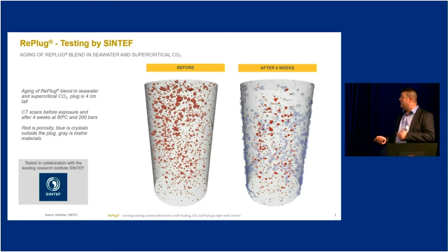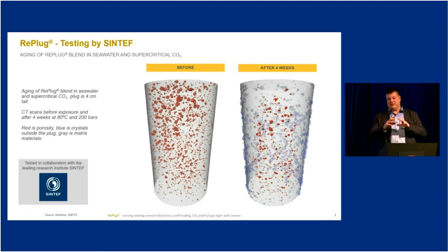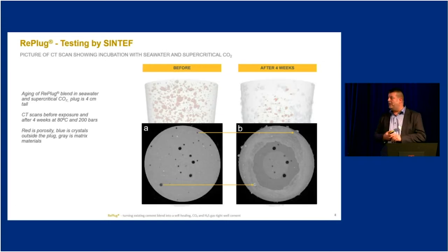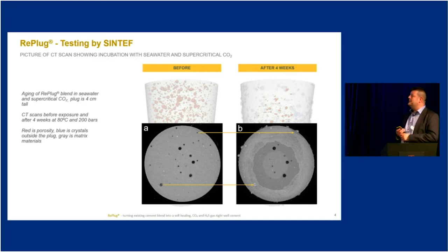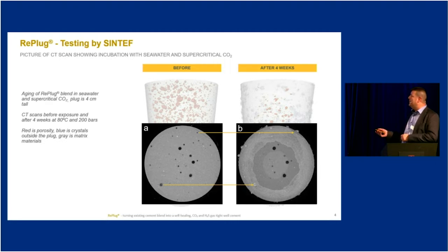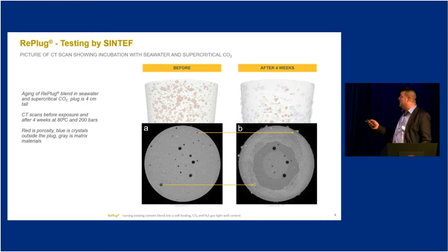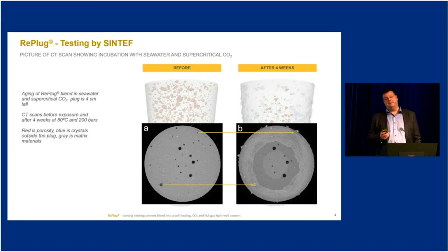Those are the ones we want to seal off. Here you can see after four weeks, there's a lot of small blue stuff — it's crystals that build. I will show you how it actually looks under a CT scanner. Here you can see there's a small crack on it. All those black ones are porosity or open voids. So you can see after just four weeks, exposed to supercritical CO2, I have actually sealed off many of those voids or the porosity. You can see from the upper yellow arrow that the crack you have is sealed off.